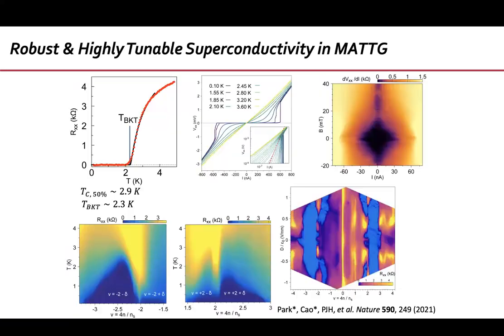Okay? Now, in this system, you get zero resistance, you get flat. Here, the contrast, unfortunately, is not very good, but you get those oscillations. Okay? It's an electrically tunable superconductor. In addition, this is all tunable by displacement field as well as filling factor. Okay? Yesterday, I was showing this type of plot as a function of filling factor or density, the number of electrons or holes per Moiré unit cell. Now we can tune the whole thing with displacement field by polarizing, by hybridizing the electronic structure, etc.